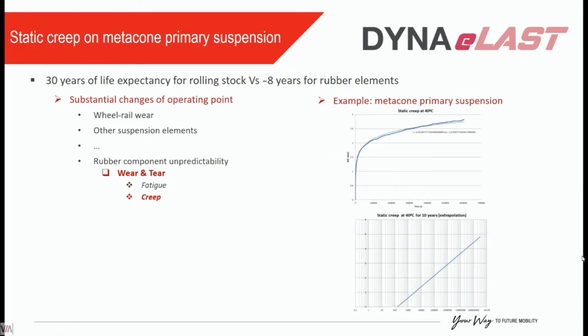We also have creep, particularly in the primary suspension. This can be very critical. The primary suspension settles, so this is a test according to the standard, where we see the evolution of the settling of the creep, and then this is the prediction for 10 years of lifespan. We've had cases in which the creep was excessive. You consume the travel allowed for the suspension, and you might end up having problems with metal-to-metal contacts. If you don't have enough travel distance for your rubber suspension, you get metal-to-metal contact, and that can be extremely dangerous from a safety point of view.